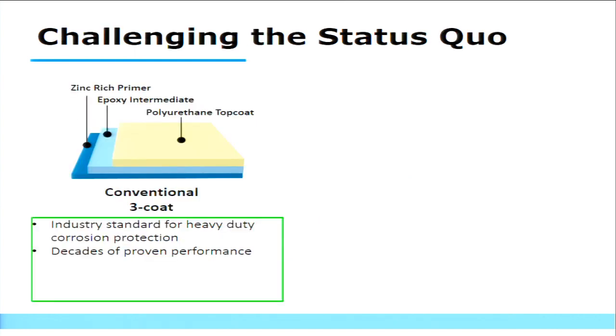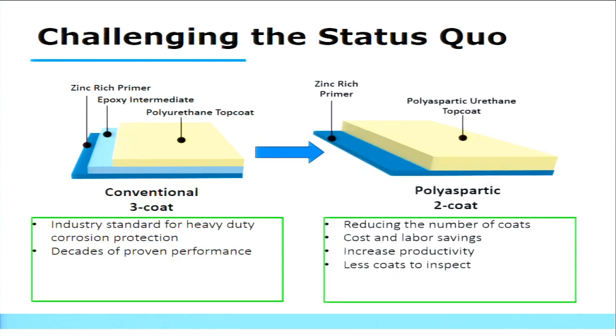So this is our traditional three-coat paint system. Zinc-rich primer, epoxy intermediate coat, and polyurethane top coat. There are some new paint systems that exist. This one happens to be a polyaspartic 2-coat. I know that this is being used somewhat in the Northeast, maybe not as much in the West, but the same zinc-rich primer, but then we have a polyaspartic urethane top coat. So obviously we have 2 coats instead of 3, so that's going to save us some time and some money.